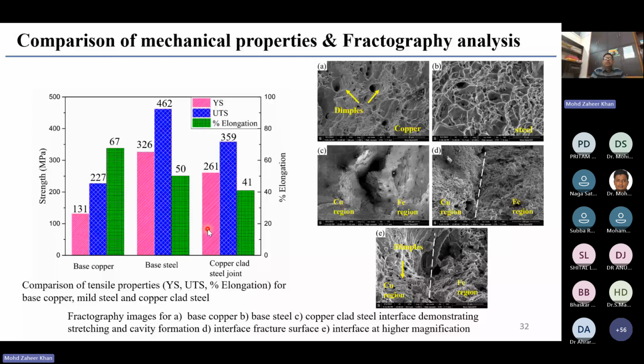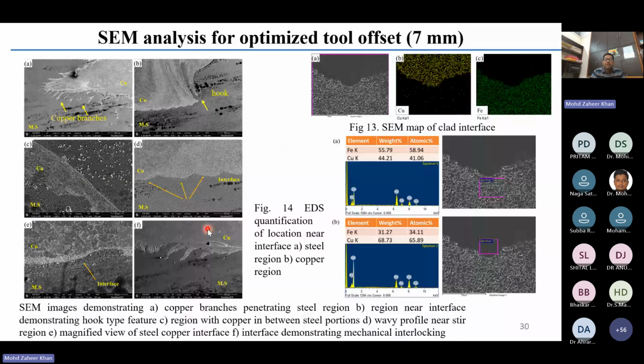This is the SEM analysis, or SEM images and mapped EDX images of the copper cladded steel. As you can see over here, a very clear, clean interface has been formed between the mild steel and copper. The mechanical interlocking that I have mentioned is also present, and even at a magnified image these have a hook type of structure. The interface is very clean, no intermetallic is at least visually observed, and more interlocking is visible in these SEM images.